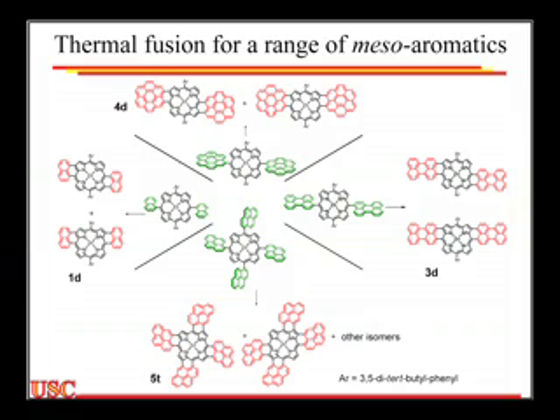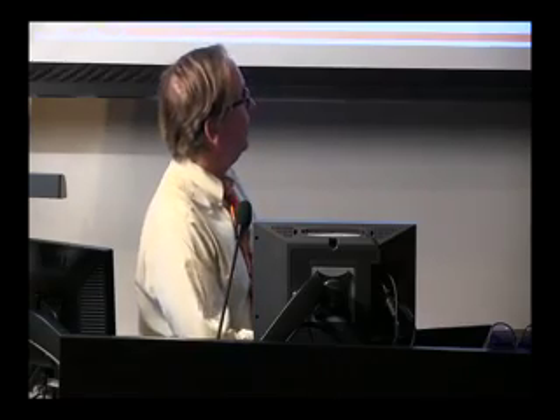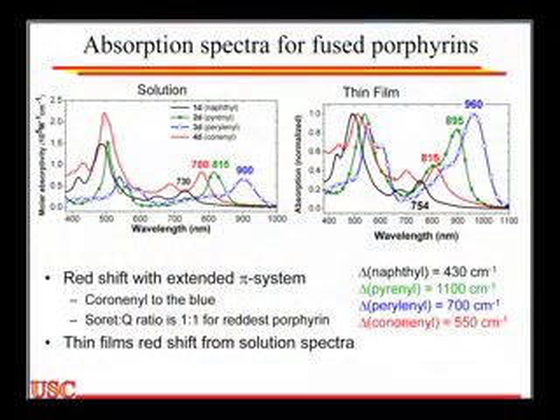This shows you our molecular modeling of the two. This is another one that we're very frustrated we don't have crystals of, and it's partly because the reaction makes 8 isomers between optical isomers and positional isomers. But if we look at it, it does exactly what we want. You can actually stop early and get the singly closed derivative. So this is the starting porphyrin, closing one end, closing both ends. The syn and anti are almost exactly the same, absorbing at about 800 nanometers.